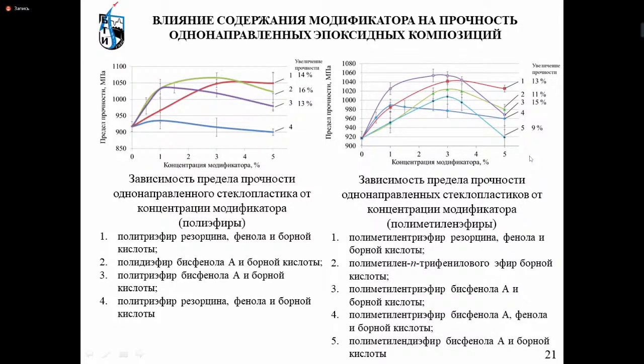And again, going back to the boron-based polymers, in the slide you can see the results on strengthening one-directed epoxide composites. The maximum growth is 13%, 14, 16%. It is connected with the epoxide composition, which is widely used and works on the edge of its strength.